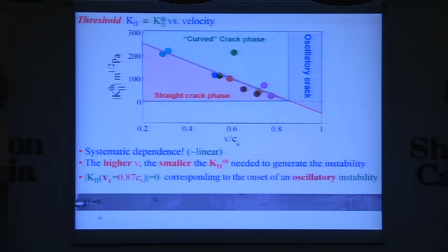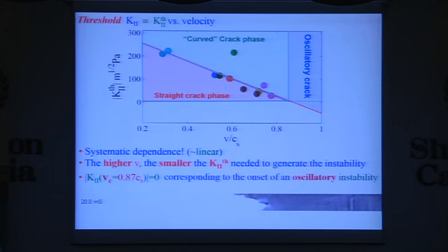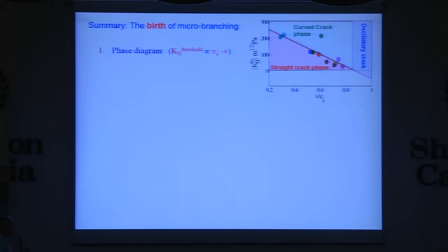Here we go. This is in milliseconds here. This is our standard parabolic crack barreling along. It's accelerating, and then all of a sudden it starts to oscillate. It doesn't branch anymore. It's a wavy crack. Now the fracture surface of this wavy crack is entirely mirror-like. There aren't any subsurface features. Basically, at this point, the entire crack starts to curve out of plane.